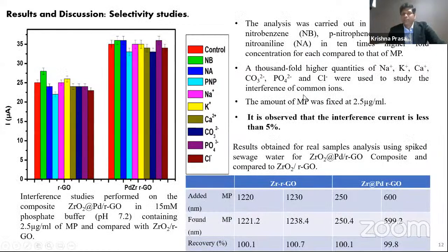And we wanted to test whether our material would go on and perform well in the presence of other interfering ions, and we have carried out differential pulse voltammetric studies in the presence of nitrobenzene, paranitrophenol, and nitroaniline in 10 times higher concentration, and we have found that the interference current is not more than 5%.